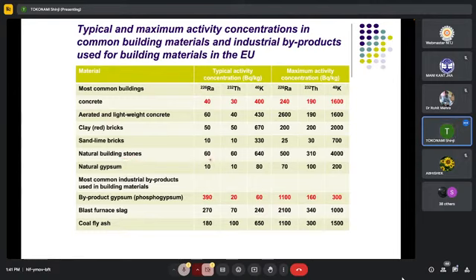Natural building stones: 60 for radium-226, 60 for thorium-232, 640 for potassium-40. As maximum activity, in the case of natural building stones, 500 for radium, 310 for thorium, and 4,000 for potassium. In the case of natural gypsum, the activity is relatively low. It is comparable to sand-lime bricks: 10 for radium, 10 for thorium, and 80 for potassium-40. As maximum activity, 70 for radium, 100 for thorium, and 200 for potassium. Common industrial byproducts used in building materials.